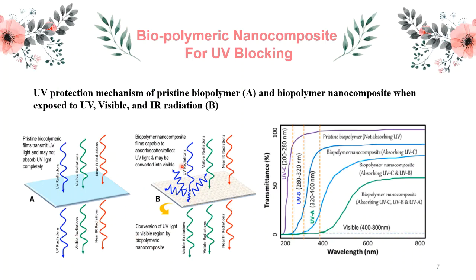However, to enhance the UV protection and blocking of these biopolymeric films, nanomaterials having an absorption band in the UV region are added. As we see in this figure, pristine biopolymeric materials may transmit all of the incident UV radiation. However, adding nanomaterials at small concentrations may increase the absorption of UV radiation in the UVC region. Increasing the concentration of nanoparticles also increases the absorption of UV radiation to be in the regions of UVC and UVB. Increasing the concentration further could extend the absorption to include the regions of UVA, UVB, and UVC.